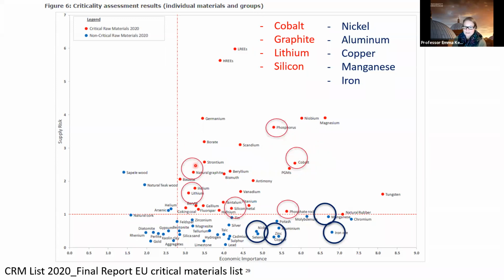Also here we've got natural graphite. Natural graphite is a key component for anode materials. You also see down here silicon metal. Silicon and silicon oxides are now used in the anodes as well as for PV materials and printed circuit boards. And what you just see creeping into the critical material list this year is actually lithium.